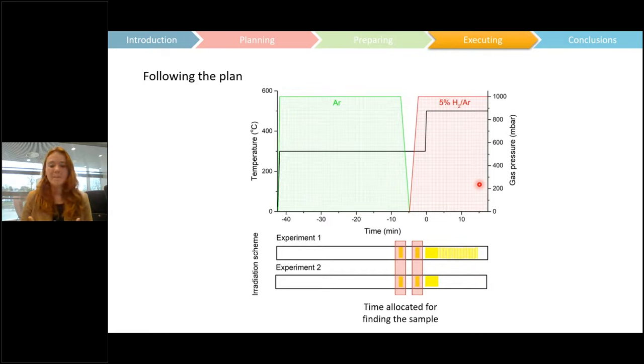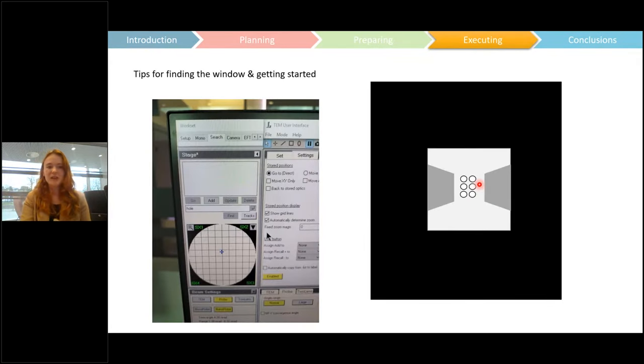And then after that, you've got some time, or at least I always allocate time for finding the sample. When I first started with in situ, I found finding the sample one of the most challenging parts. So I've developed a bit of a technique for finding the sample. You don't have to follow this. If you're someone who just switches on the beam and already sees your six windows in the center immediately, great. Our microscope isn't calibrated like that, so we often end up somewhere off the window. If you end up in the black where you see nothing at all,